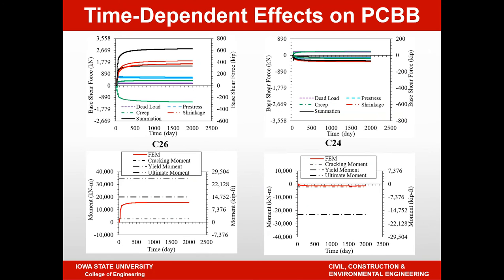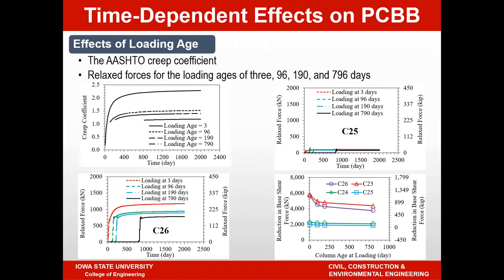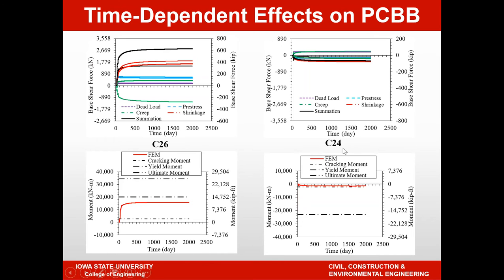The next figure highlights the corresponding forces, and you can see more clearly the base shear forces. Let me just go back to the previous slide. So this one shows the base shear force in column 26 and column 24. You can see the different deformations taking place, and the black line gives you the summation of the base shear force, and likewise you see the black line here that gives you the summation. In this particular case, you can see that the two columns see very different magnitudes of forces, so that's one thing to realize. The further away the column is, the higher the forces developed, because of the higher deformation on the columns.